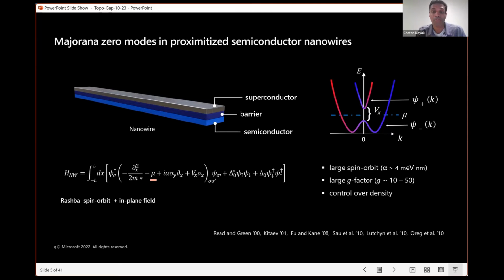And as a result, if you can control the density, you can arrange for the chemical potential to be in a place, or the density to be such that the chemical potential only intersects the band in exactly 2 points. So there's exactly 2 Fermi points, not 4 or a higher number. And when you only have 2 Fermi points, and you have a good interface with superconductivity, that superconductivity will necessarily be topological. So the name of the game here is construct some band structure with only 2 Fermi points, induce superconductivity, and you've got something topological. This is a highly simplified model, very idealized. However, what I'm going to explain now is how we can design a device that actually makes this, that makes reality look like the simplified model.